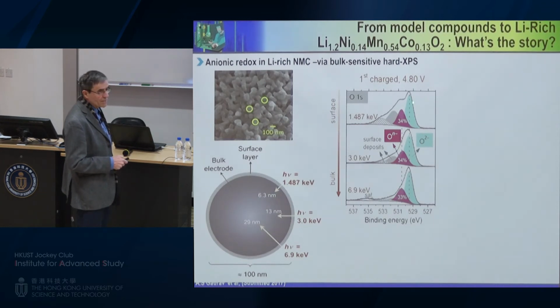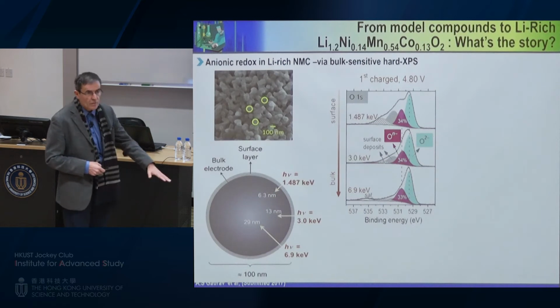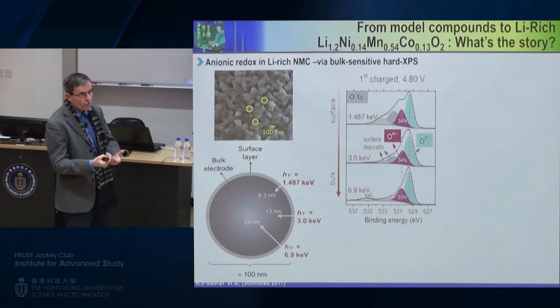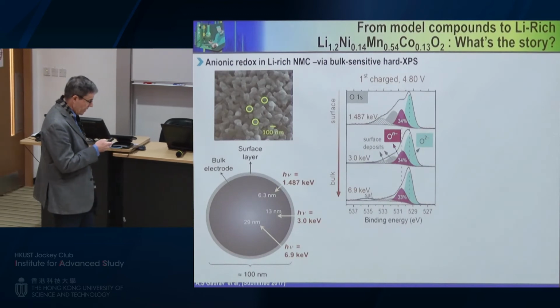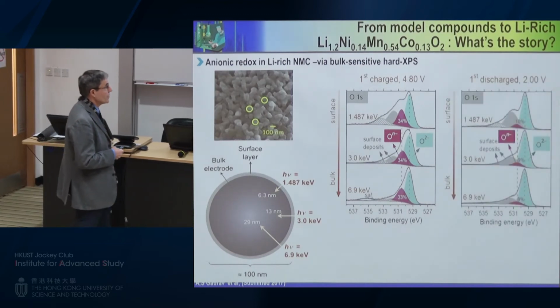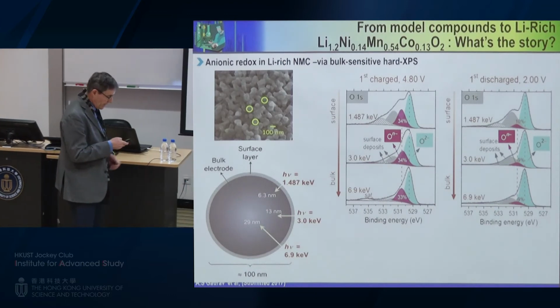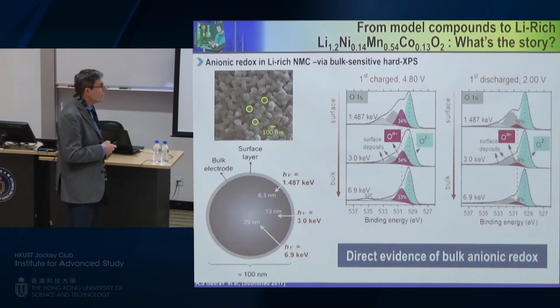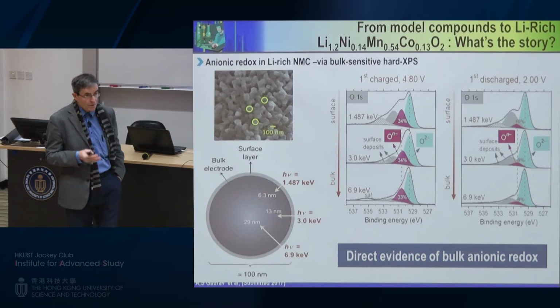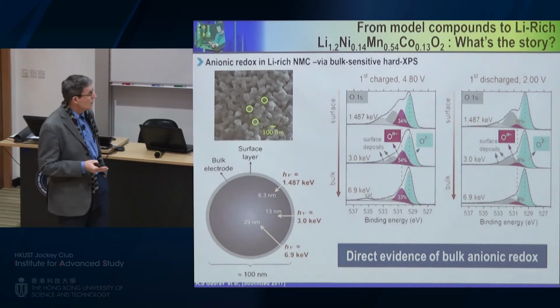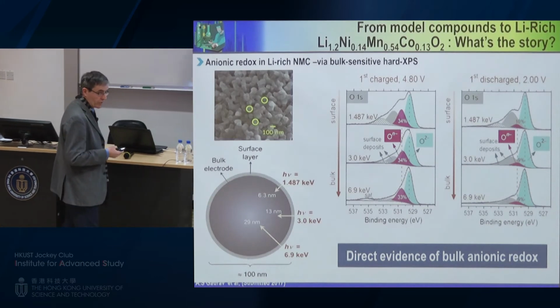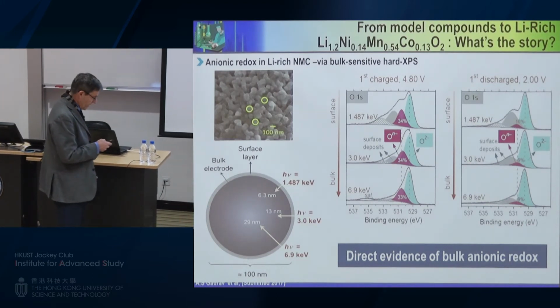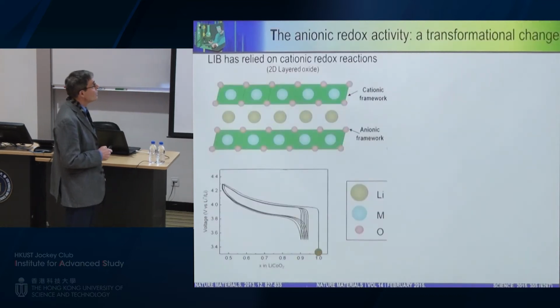And of course, you can see here that by working with this very high intensity, we get rid of the effect of the surface, because we go deeper into the material, and the proportion of the surface becomes smaller. And this is really perfectly reversible. So I think by now, and there is some more data coming in the literature, that we have direct evidence that even in a lithium-rich NMC, we have a bulk anionic redox. So this is to conclude this story about the paradigm.